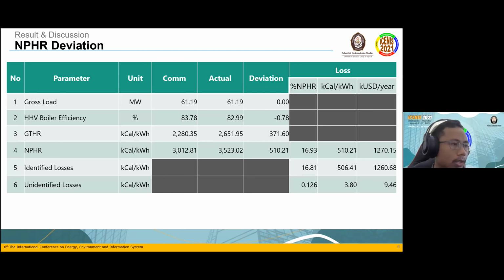The actual performance test heat rate increase compared to the commissioning was 510 kilocalorie per kilowatt hour, or 16.9%. This increment is due to boiler efficiency decreasing by 0.78% and turbine heat rate increasing by 371 kilocalorie per kilowatt hour. Identified heat loss was 506 kilocalorie per kilowatt hour, while the unidentified loss was 3.8 kilocalorie per kilowatt hour. Annual fuel cost increase obtained is 1.2 million USD due to the actual heat rate increase compared to the commissioning value.